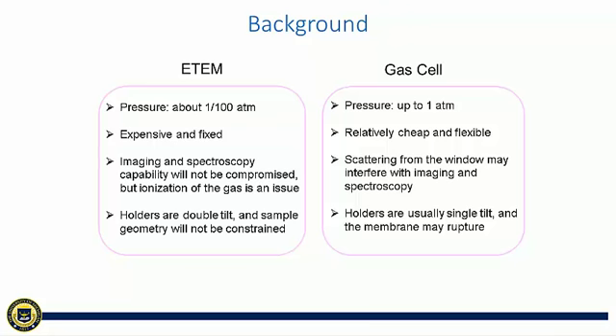For the ETEM, most of the holders are double tilt, so you can orient your sample at your preferred orientation. But for gas cell, the holders are usually single tilt, and the sample geometry are constrained. There is also a potential danger of membrane rupture.